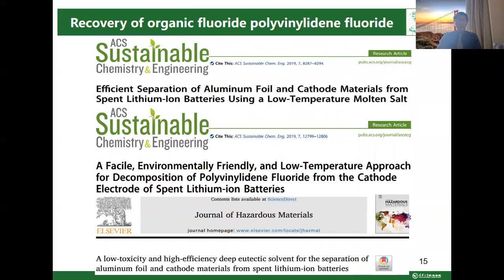Here is an example of the recycling technology that we have been working on. Here is a molten salt process we propose that can achieve the separation of aluminum foil and cathode material at a low temperature of 160 degrees Celsius. A calcium oxide-based alkali medium can achieve the clean degradation of PVDF and the capture of fluoride. The deep eutectic solvent, as an environmentally friendly and low cost reagent, can realize the thermal degradation and the clean recovery of PVDF. This is a series of papers published in this area.